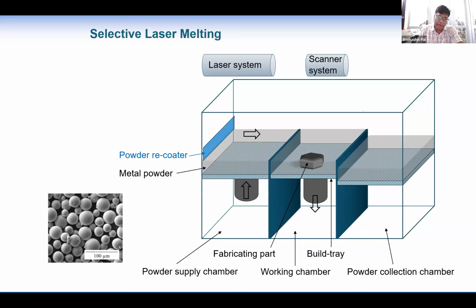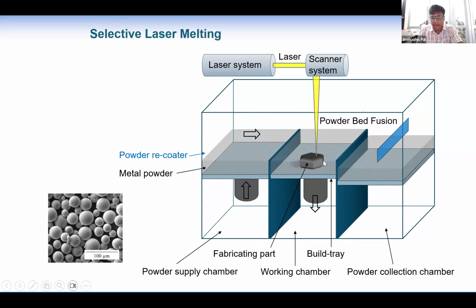So we keep this powder here, and then the laser will melt the part accurately, according to the requirement. One layer will be scanned by laser melting, and then another layer will be deposited and melted again. After that, the piston will move down a little bit, say 25 micron, and again another layer of 25 micron will be deposited and melted. Like this, the process goes on.